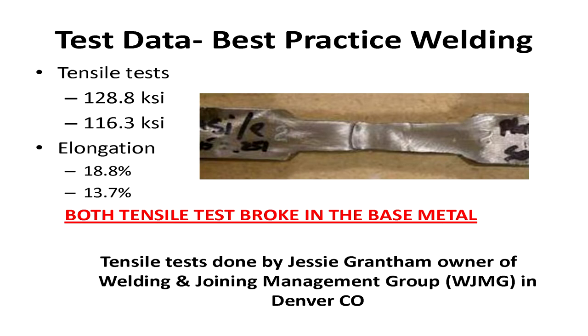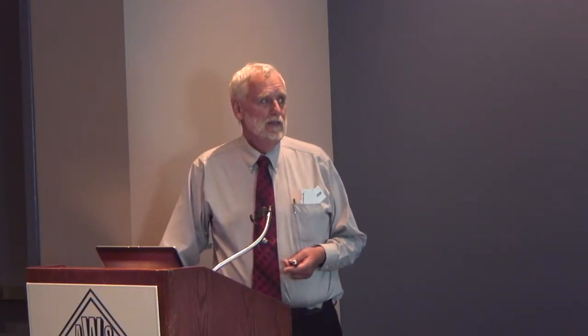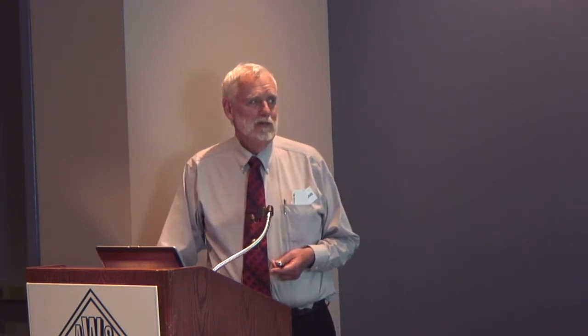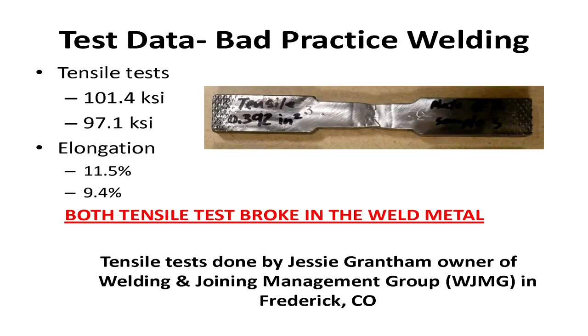The best practice, look at the tensile strength. 128K. Isn't that sweet? 116. And they both broke outside of the fusion. Elongation. I had this Welding & Joining Management Group out of Denver do my testing. Just such a good old guy. We went to school together. The bad practice, look at the elongation. It's not that it didn't elongate, it fractured before it could stretch. I was even surprised, welding it with 7018, it still broke at 97K.